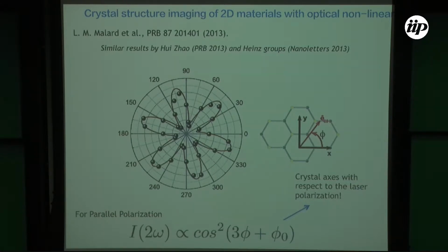Okay, and so we did this polarization measurement on this sample. Basically we fixed the input laser polarization at some angle with respect to the sample, and then we rotate the sample. Then this is the polar plot of the intensity of the second harmonic as a function of this angle phi, which is the angle between the armchair direction and the laser polarization. Okay, and then you have this threefold pattern.